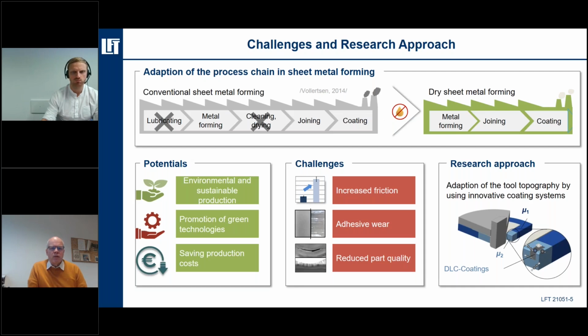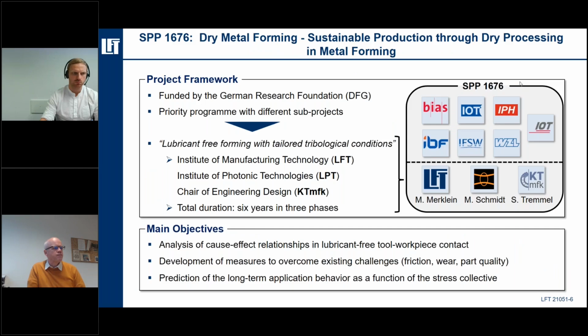So the idea is, what can we do to the tool? How can we modify the tool to reach the conditions we would like to have? And the idea there is, okay, we could use some coatings, because if we think again of the sandpaper, it's also the surface and what we put on there, while the paper underneath isn't changed so much. To address this research question, how can we adjust the tool topography by using coating systems, we had a large research group consisting, as on the next slide, of 10 institutes, 3 of them located in Erlangen.